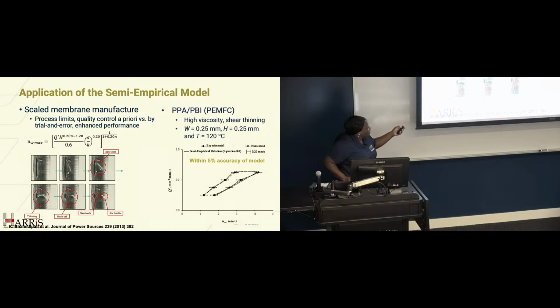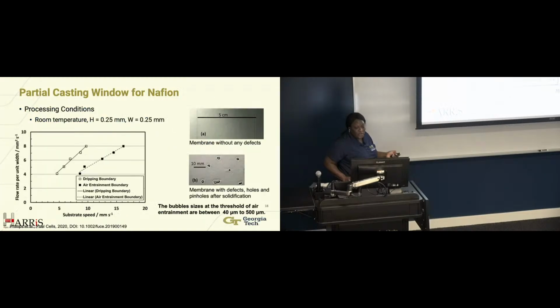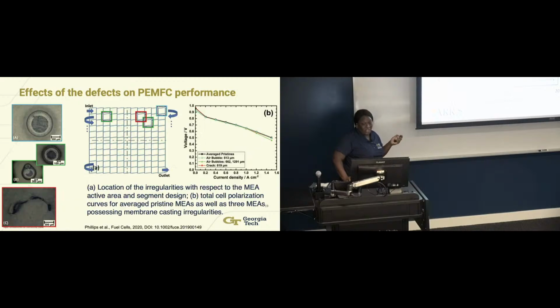This cartoon shows that sawtooth formation and how it continues to grow. Ultimately, there's a pinch point where you get the release and the break of the bubble into the film. These films here are all just standard solutions, nothing extra. But we then took similar material and measured the pinholes and the air bubbles that were present so that we could get an idea of how large they were and begin to create artificial ones to test. Unfortunately, whenever you're processing materials experimentally, you're not going to get the same defects at the same points every time. So we wanted a more controlled study with NREL to do this testing.